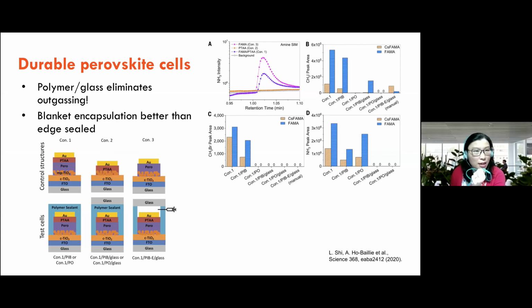So what we find is, if we put a glass on top of the polymer, there's no outgassing. So that one with the glass, you can see there's no outgassing. The edge-seal one, you can see a little bit. So this represents the edge-seal. You can see a little bit of CH3I coming out.